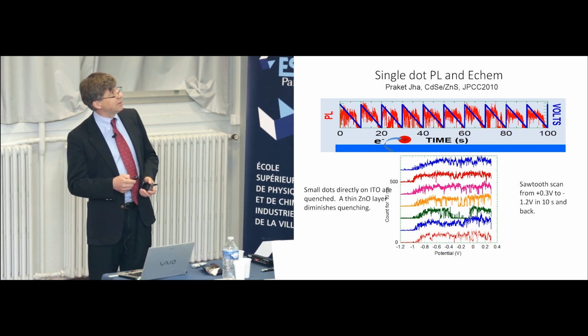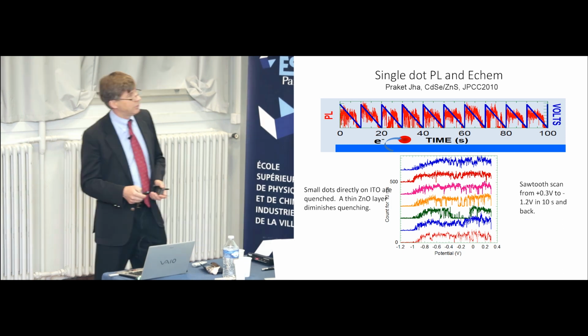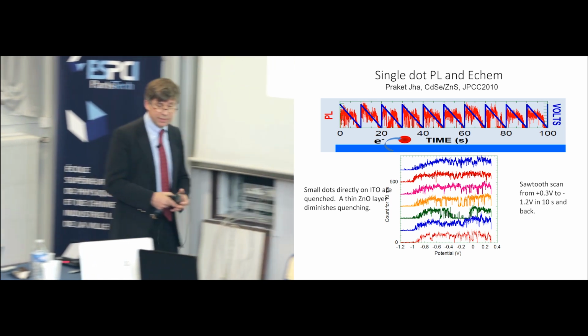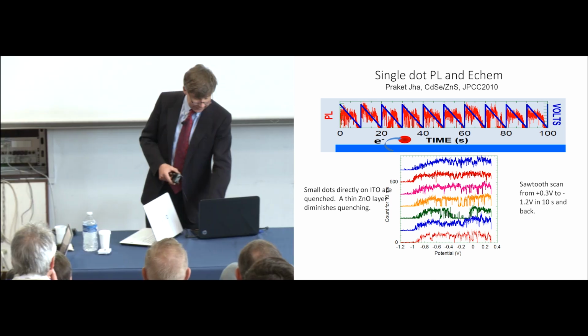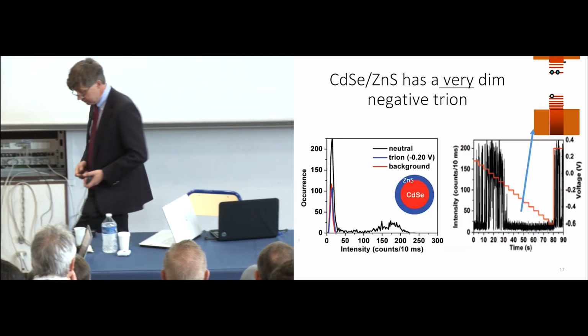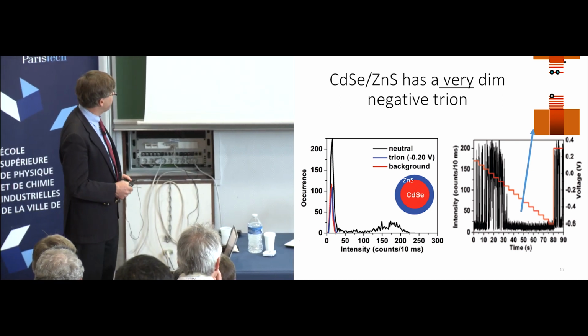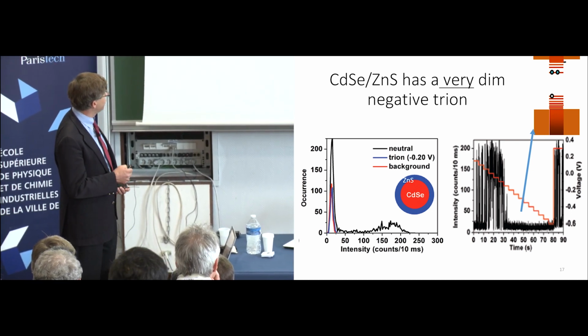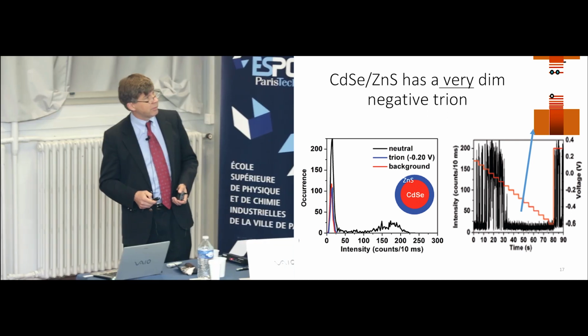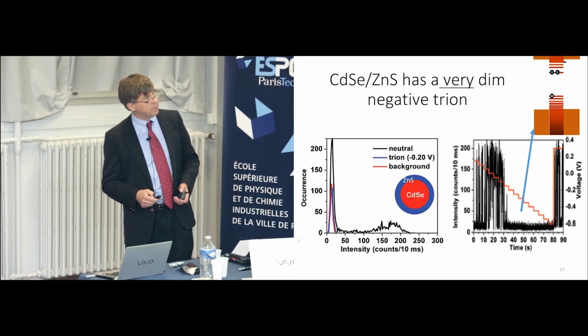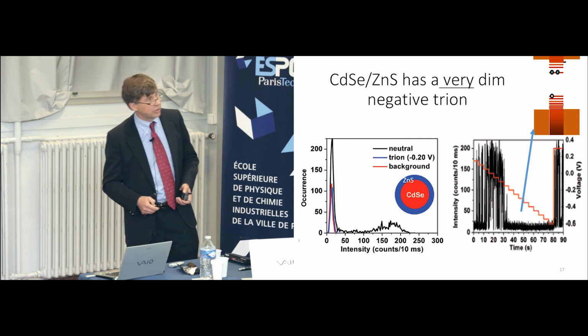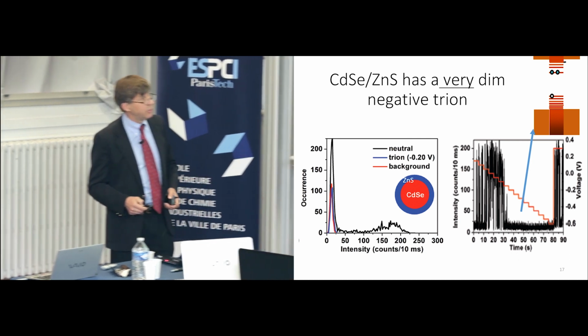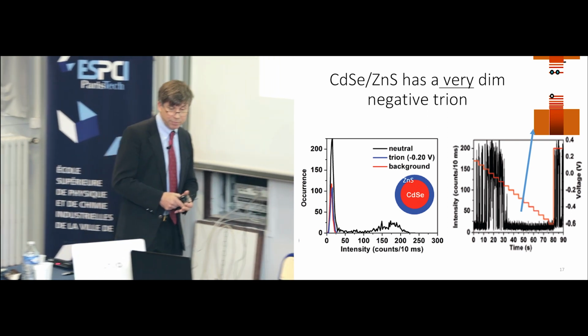And what we saw was that the dot could very well be charged and turned off on a regular basis like this. But the charged dot in this case, with the zinc sulfide cap, was just plain too dim to see. And so this is the spectra of the dots uncharged, and when it's charged, it's just matching the background level. This is the dot blinking as the potential is stepped down to the reducing potential, and at some point it just stops blinking, stops emitting altogether, and then it comes back.